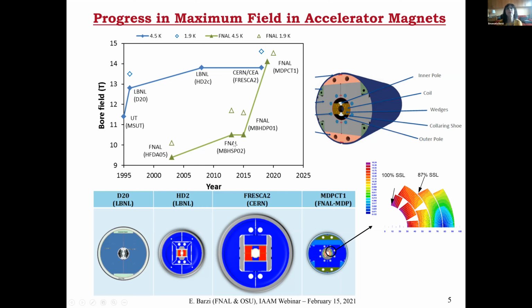So we had a very slow start, you can see here. Then we found out what was wrong, both in the superconductor and in the magnet technology, which is very complex. And we were able to achieve a world record, whereas our counterpart, Lawrence Berkeley National Lab, started much faster, nearly 30 years ago. They started very well, and then they reached a plateau. So this is to give you an idea of how progress can evolve in different groups. And this is an example of the complex system that these magnets are.